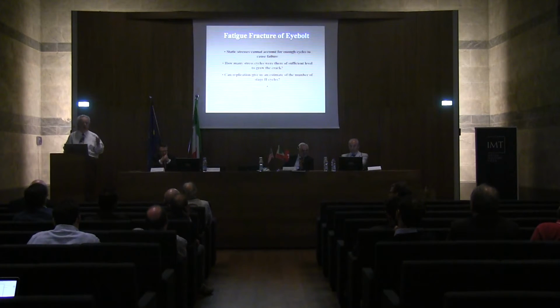And of course, when I got this job, the failure occurred 12 years before we were given the samples. So you wonder, what kind of quality is that fracture in? And the man had cut a piece out at the origin, and also the final rupture zone. Fortunately for us, he coated the fracture with grease. So when I got it, I could clean the grease off, and I could replicate it and see fatigue striations.